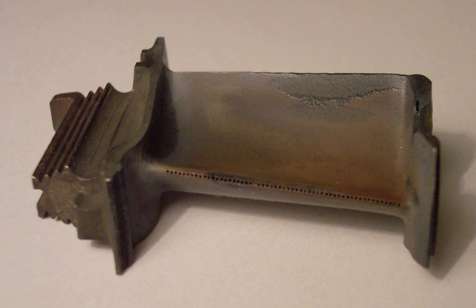In these alloys, W is the crucial addition for getting the gamma prime intermetallic compound, which makes them much denser, greater than 9.6 grams per cc, compared to Ni-based superalloys. Recently, a new class of gamma-gamma prime cobalt-based superalloys have been developed that are W-free and have much lower density comparable